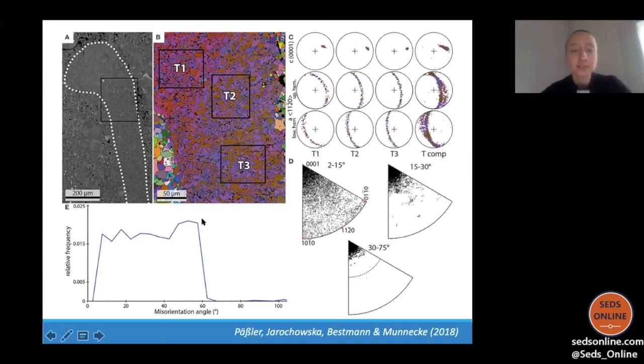Interestingly, in all of these specimens, just the range of misorientations and the distributions of misorientations did not show any substantial differences. So even though this is mostly reported in papers, it was not indicative to answer our question. When I went back to look at other people's papers and compare our results, I was very often finding the distribution of misorientation angles, but very rarely would the orientations of misorientation axes be reported. So I would be really curious to hear from people who do similar research and have been looking at these parameters as well.